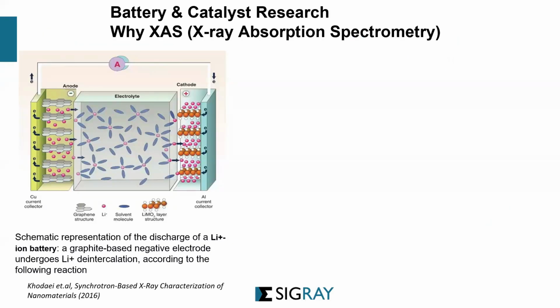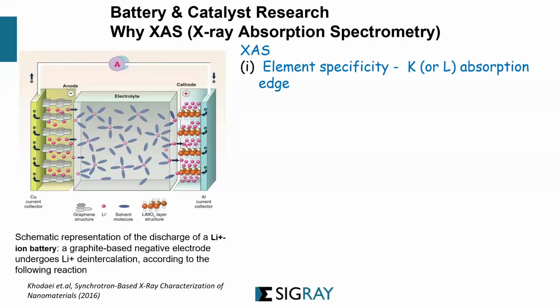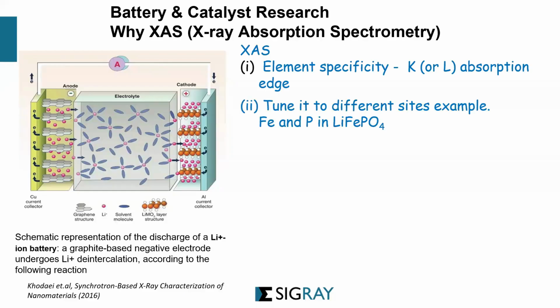Let's go back to battery or catalyst research. What is X-ray absorption spectroscopy, and why use it? You find that it is very versatile, because you can study a very specific element, whether you want to do the K shell or the L shell absorption edge. And you can also tune into the different sites. For example, the traditional battery material that is used commercially is still lithium iron phosphate. We cannot study the lithium, but we can look at the other sites like the iron or the phosphorus component, and you can tune specifically into them.